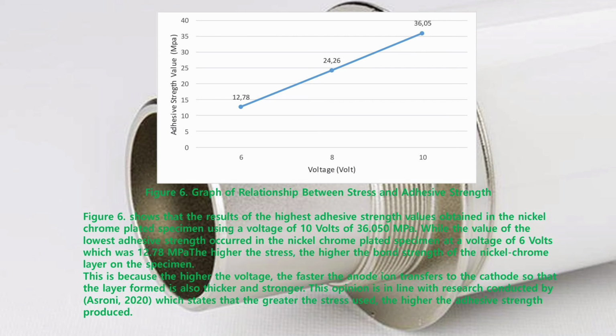Figure 6 shows that the highest adhesive strength value was obtained in the nickel chrome plate specimen using a voltage of 10 volt, of 36.050 megapascal, while the lowest adhesive strength occurred in the nickel chrome plate specimen at a voltage of 6 volts, which was 12.78 megapascal.